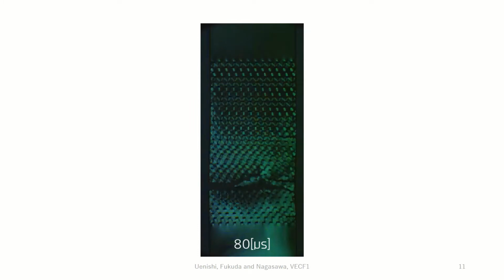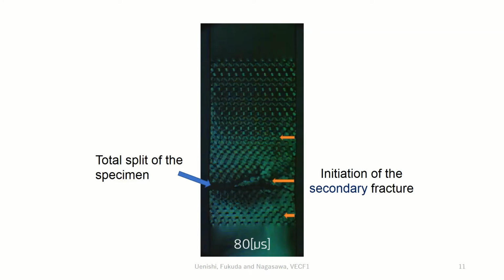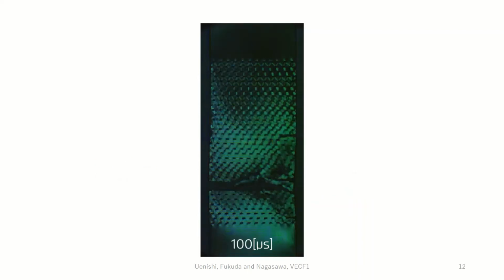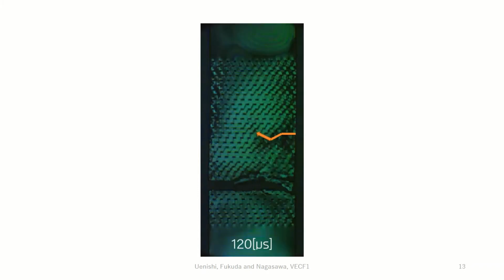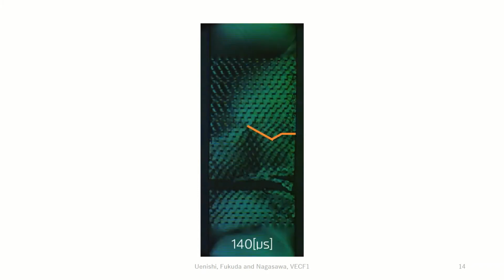Here, at time 80 microseconds, total split of the specimen by the primary fracture as well as the initiation of the secondary fracture, which will propagate to the opposite direction, can be identified. At time 140 microseconds, the propagation of the secondary fracture arrests. Surprisingly, this arrested secondary fracture will resume its propagation in 200 microseconds, although no additional external load is exerted to the specimen.